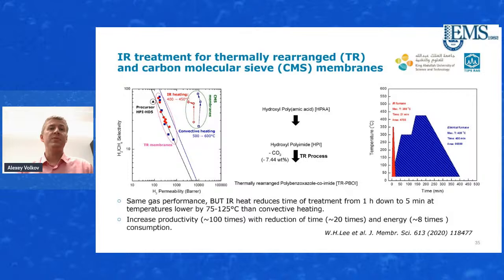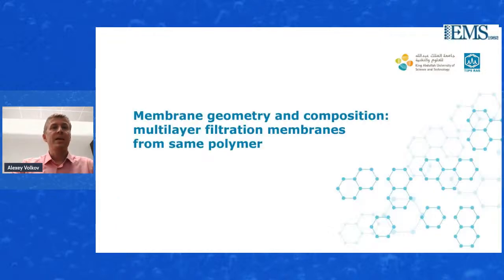And we increased the productivity of the fabrication of the membrane by a factor of 100, with a reduction of the time by a factor of 20 and energy 8 times lower. So it means that we can use that approach not only for the PAN material, but also for materials that require thermal rearrangement as well. And that's a part I like a lot, because when we started to work with the PAN and started to make it insoluble, I was thinking, okay, we use different materials to make a support layer and the selective layer, but can we use the same material to make the support layer and also the selective layer?